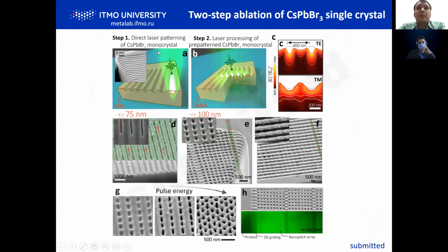Also, such micro plate nanostructuring by laser is possible not only in a single step of direct cutting by a laser with a stripe-like focus, but also by two-stage laser ablation, when we rotate the stripe after the first processing. In this case, light focuses additionally in each grid of this grating, and we see additional localization beneath each stripe. And we can create nano holes and something like two-wavelength structures, which can work as metasurfaces after proper adjusting of geometrical properties.